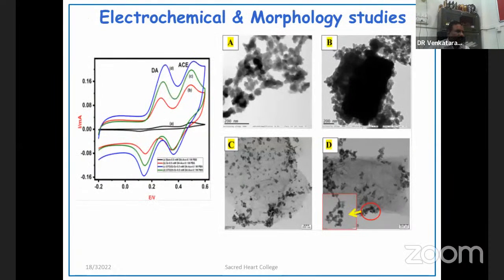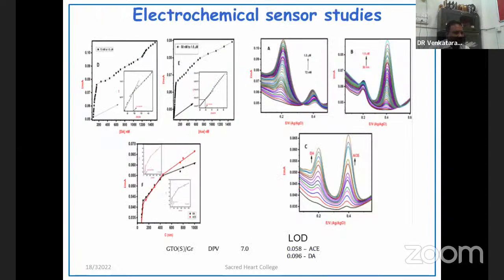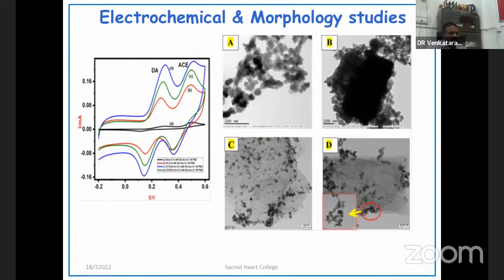So here we measured again dopamine and acetaminophen, where the morphological changes result in an LOD of around 0.058 micromolar for acetaminophen and 0.096 for dopamine. This is how we try to develop a sensor, but these were evaluated in urine and blood samples. We collected urine and blood samples and we try to measure the concentration of dopamine, especially the dopamine in